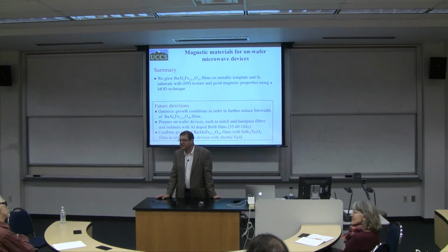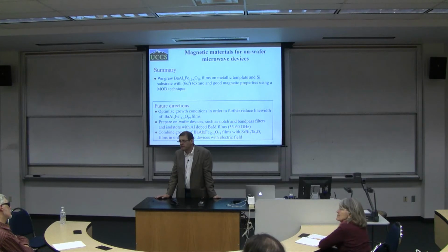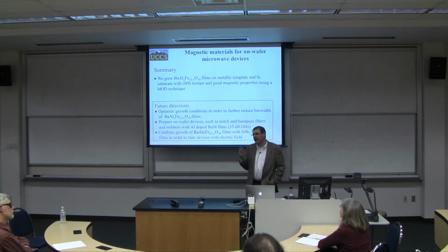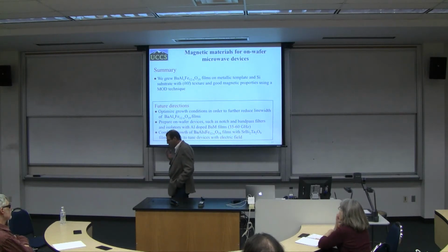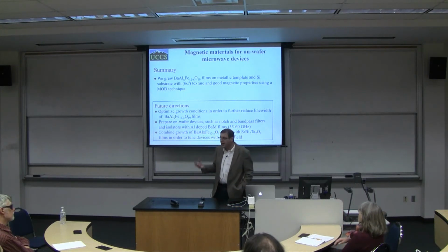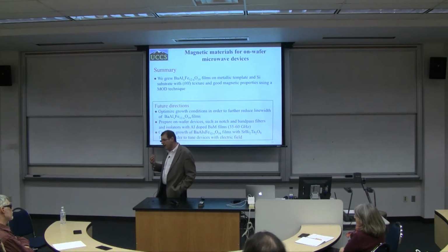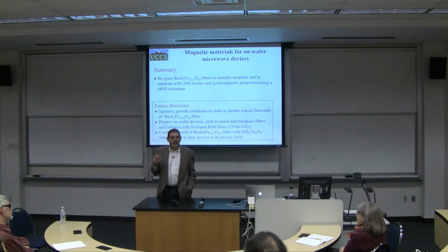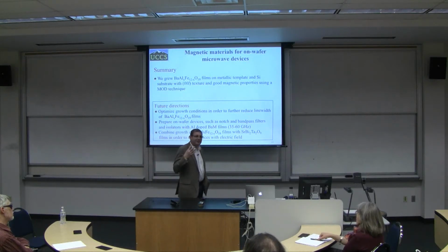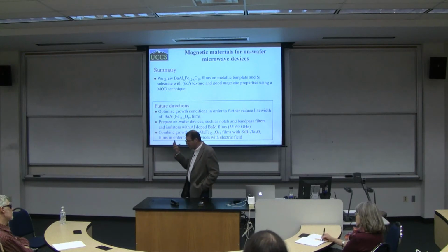When you have saturation, is that mainly in the electrons, in the orbitals, and their behavior? Yes. In other words, if you have a magnetic ion, like iron, why are certain atoms magnetic and others are not? What's the difference between copper and iron? The pure difference is the number of electrons you have in the 3d shell. For iron, this 3d shell is not completely filled up, and these moments are very well localized, and therefore their orbit has a particular shape.